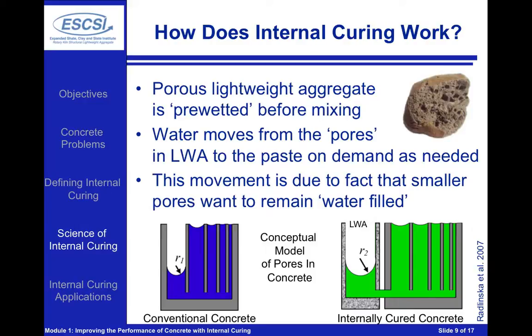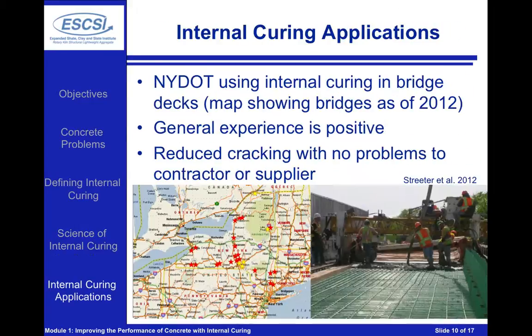However, once the concrete starts to set, these vapor-filled spaces can start to develop because of chemical shrinkage, leading to the self-desiccation that we're talking about. However, the lightweight aggregate has water, and that water can be supplied to the matrix. So water will move from the pores in the lightweight aggregate into the matrix as it's needed, and this will reduce the pressure that develops inside of the fluid. This will keep the paste pores filled, and this will reduce the effects of self-desiccation. Now, some of the advantages of this, it's going to allow more of the cement to hydrate. In addition, it's going to reduce the overall shrinkage stress that's developing.